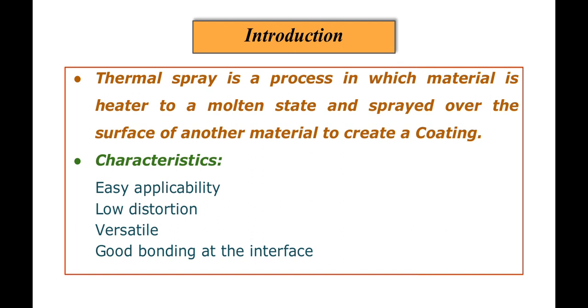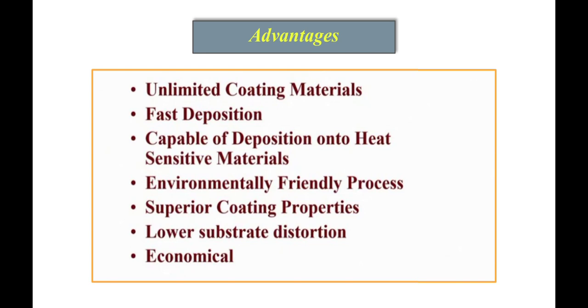Usually this is a versatile technique, as I have mentioned, because it can be applied for a wide range of materials, from polymeric materials to high melting ceramic materials. Deposition speed is very fast. There is a negligible heat affected zone. The process is very environmentally friendly, with superior coating properties, low substrate distortion, and it is much more economical as compared to high-end processing like laser or electron beam processing, and it is capable of deposition on heat sensitive material also.